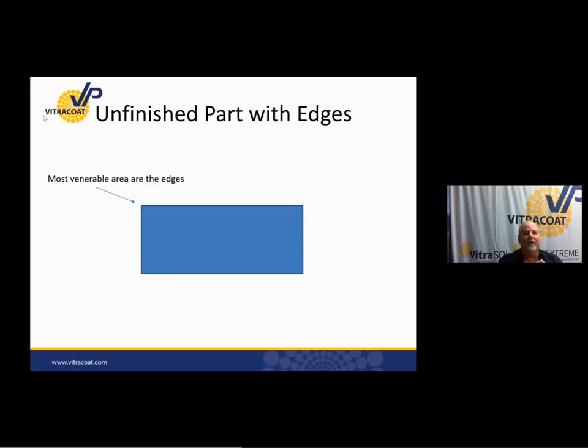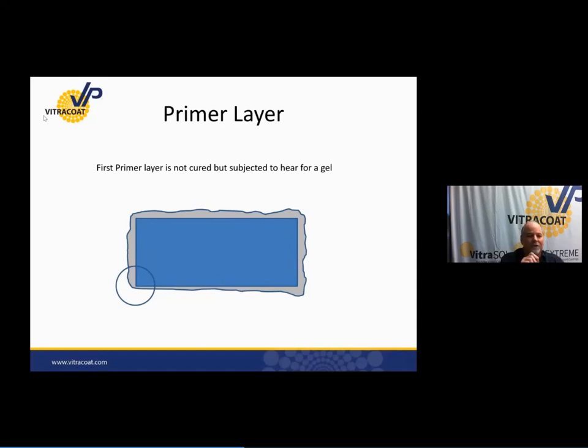Well, let me try to illustrate what it would do if I put on a primer first and I gelled it and then a top coat on top of that. So if this square box is my part, I have 4 very sharp 90-degree angles or edges. If I put on that primer first and gel it, it's going to look something like this. A variety of different film thicknesses, but on the edge, I'm still very thin, even with my primer layer. Now, I can make that primer layer shorten gel so that it does hang better, perhaps puts on a higher percentage of the finished product on the edge.